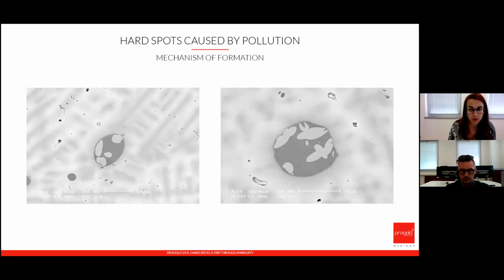All the solid particles rather stay together than be dispersed, so they accumulate at a certain point. These particles are not soluble inside a melt, so they are just spit out, and they remain as a different phase in the alloy, and we see them as hard spots.